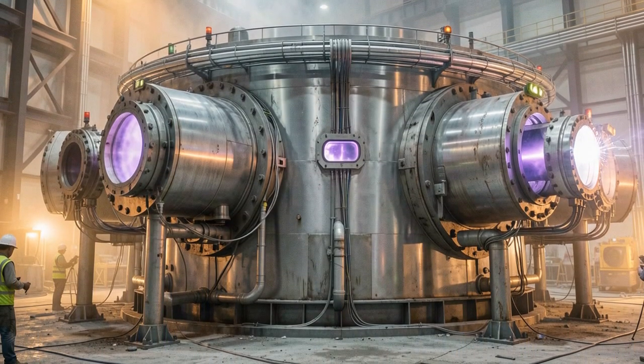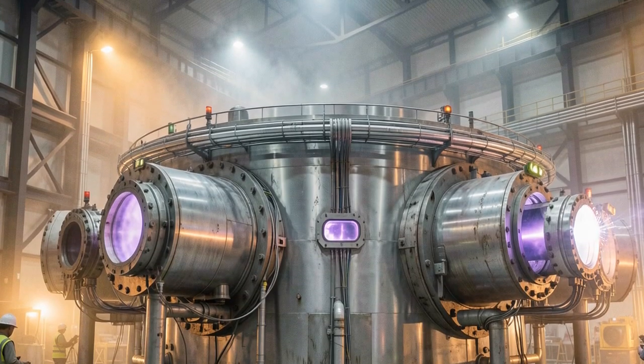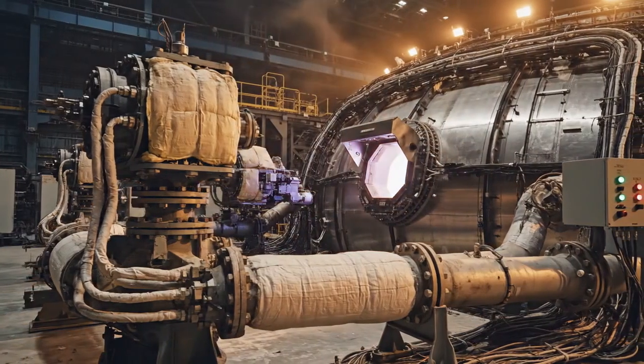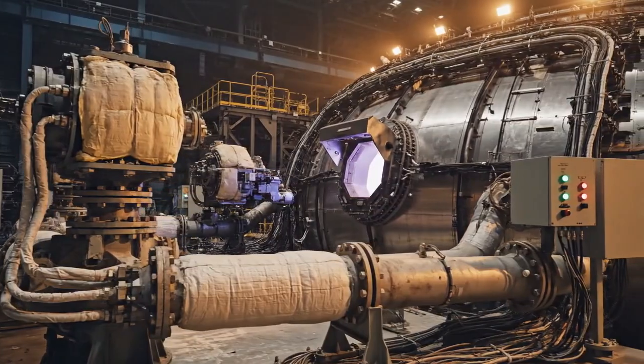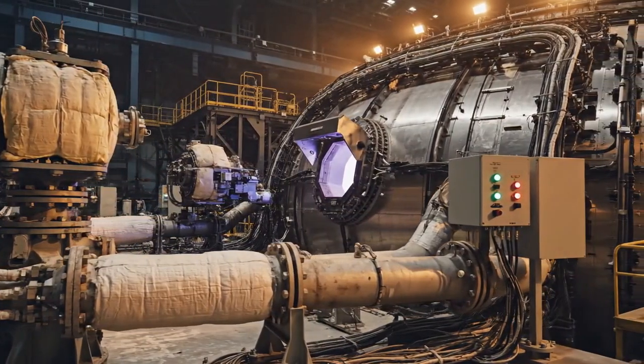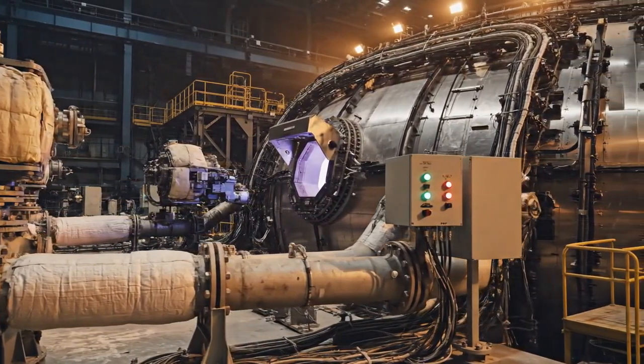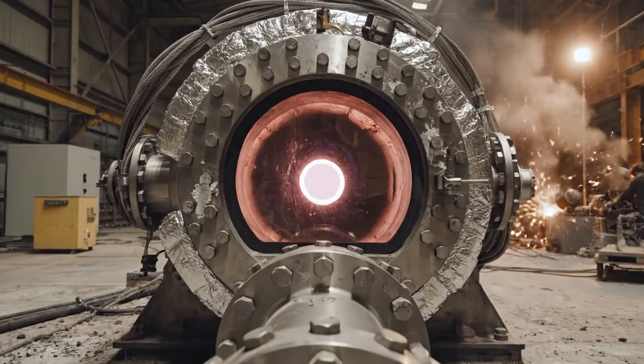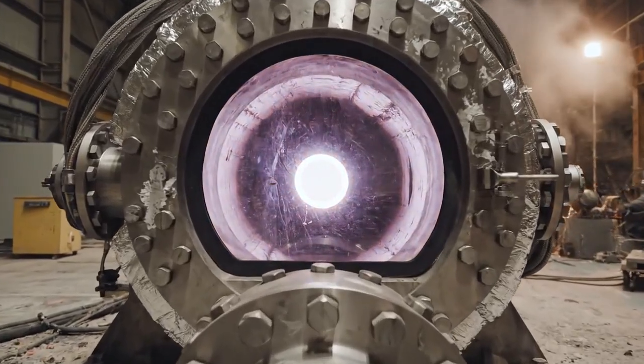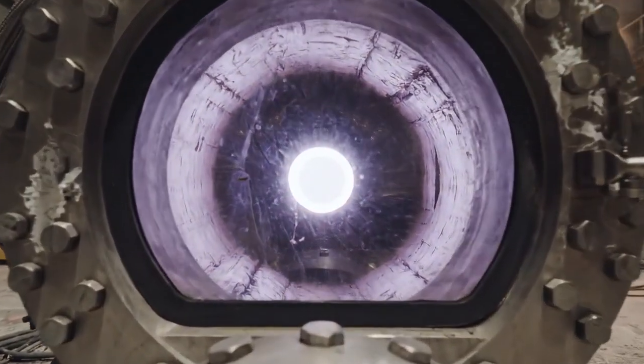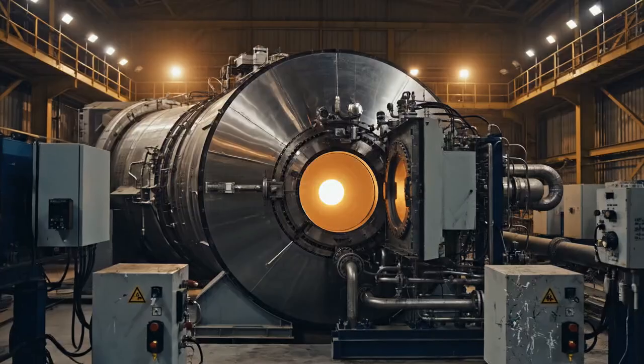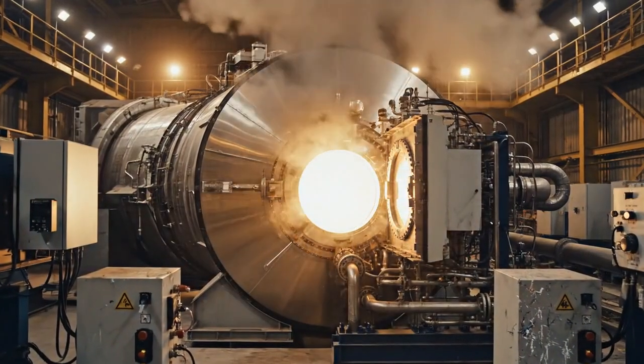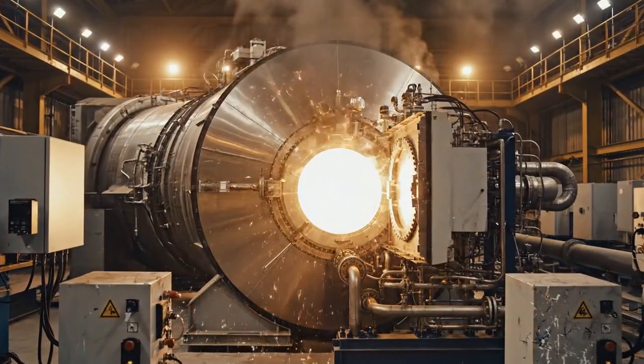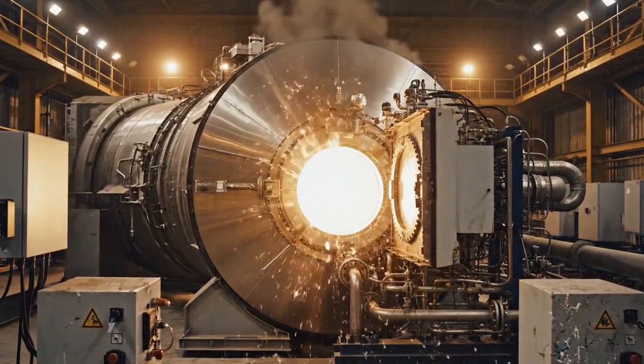The critical obstacle comes during the first plasma tests at high magnetic field. Midway through a sustained plasma discharge, an arc fault develops in the power supply system feeding one of the poloidal field coils. The fault deposits energy into the coil faster than the quench protection system can respond. The coil warms above its superconducting transition temperature. Suddenly, it is no longer superconducting. The resistance reappears. The stored magnetic energy begins converting to heat inside the conductor.